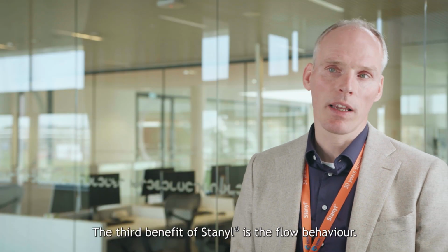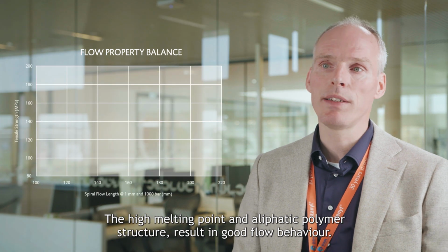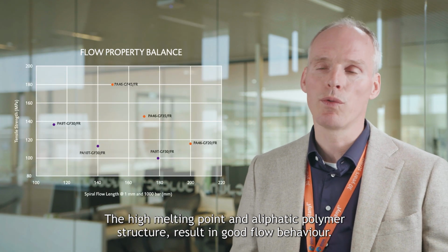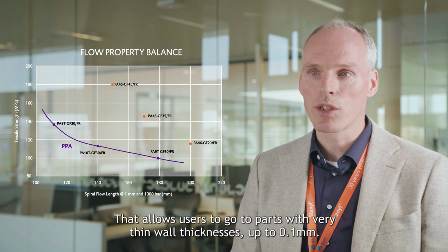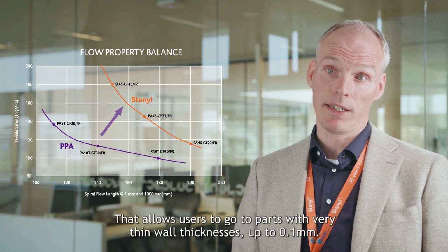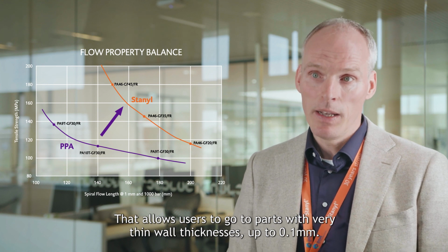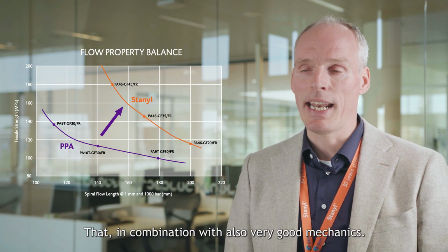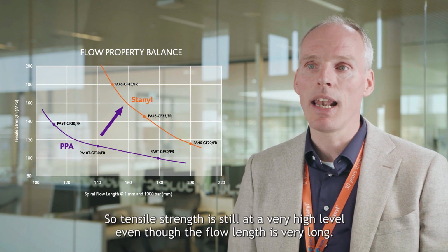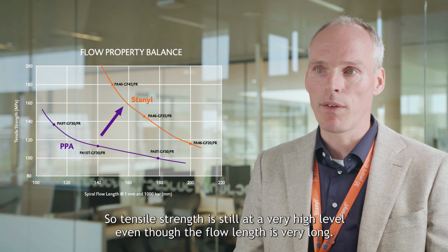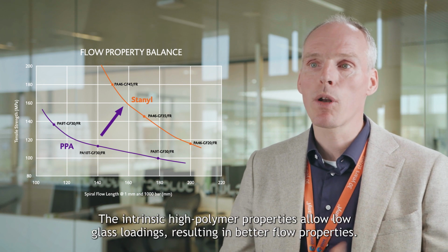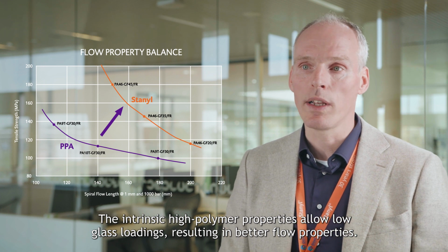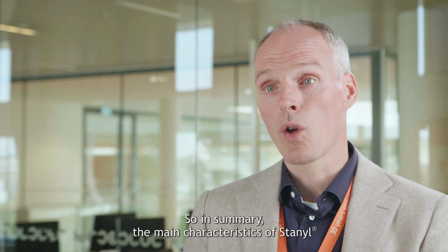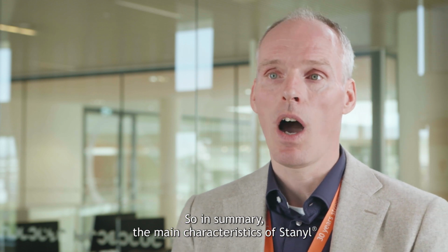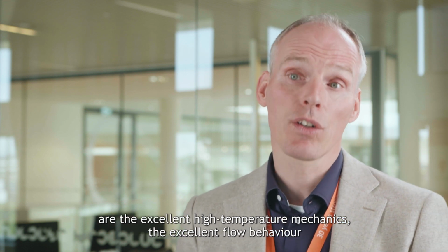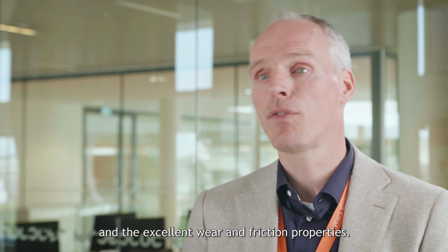The third benefit of Stanyl is the flow behavior. The high melting point and aliphatic polymer structure result in good flow behavior. That allows users to go to parts with very thin wall thicknesses, up to 0.1 millimeter. That in combination with also very good mechanics. So tensile strength is still at a very high level, even though the flow length is very, very long. The intrinsic high polymer properties allow low glass loadings, resulting in better flow properties. So in summary, the main characteristics of Stanyl are the excellent high temperature mechanics, the excellent flow behavior, and the excellent wear and friction properties.